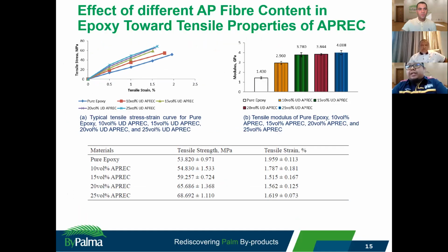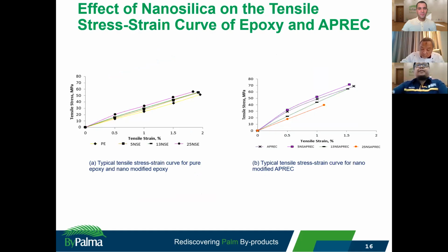From the result shown in the slide, 25 volume percent APREC gives the best tensile properties, which increased tensile modulus by 180.28% and tensile strength by 27.63%, compared to the pure epoxy specimen. So that's why we are using 25 volume percent for our nanosilica modified APREC. After we place the APREC, we get the result. This slide shows the typical tensile stress strain curve for pure epoxy.